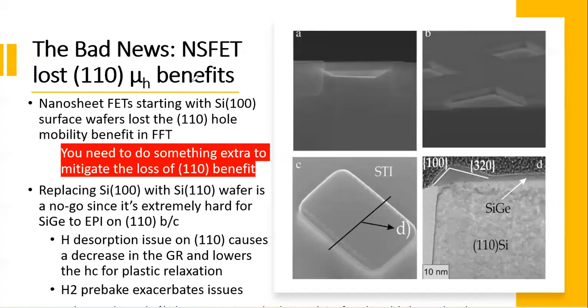So what does that have to do with nanosheet? Well, in nanosheet you lose the 110 benefit because your nanosheet is flat. Your surface is 100. For FinFET, the wafer you buy is 100, but you are etching the wafer to form a fin, and that fin can be oriented in any direction you want. You choose the FinFET 110 surface for your fin, so you get a hole benefit. But you cannot do that in your nanosheet when you come with a 100 surface.